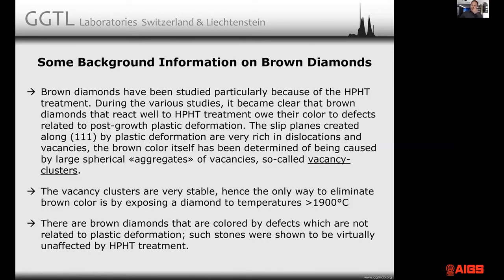Now let's give you some background information on brown diamonds. Brown diamonds have been studied in the past, particularly because of the HPHT treatment. Before, actually very little has been done on them. The most interest has been triggered in those diamonds to understand, and first of all, to understand the treatment, and second of all, to be able to identify the treatment. So during the various studies, it became clear that all brown diamonds that react well to an HPHT treatment owe their color to defects that are related to post-growth plastic deformation.